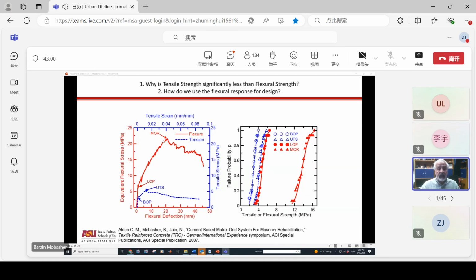And for example, these are some data that we published a long time ago again, where for the same specimen, tensile strength is about 5 megapascal, and the flexural strength is about 20 to 23. So if I'm designing something with this, I can design it with this calculation. But the problem is I can't treat this value of strength, MOR, as an elastic equivalent stress. That's a huge mistake that we would make. It doesn't mean that I can design it with a tensile strength of 20 corresponding to this value. This is an equivalent flexural stress that we get out of the material here.